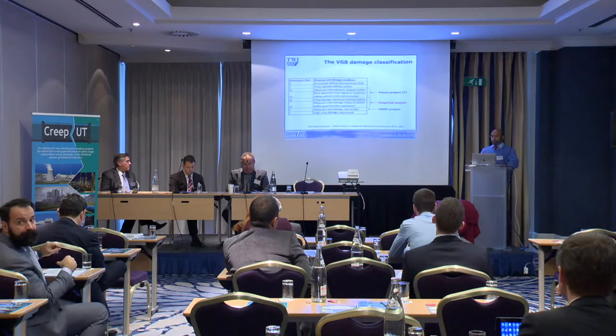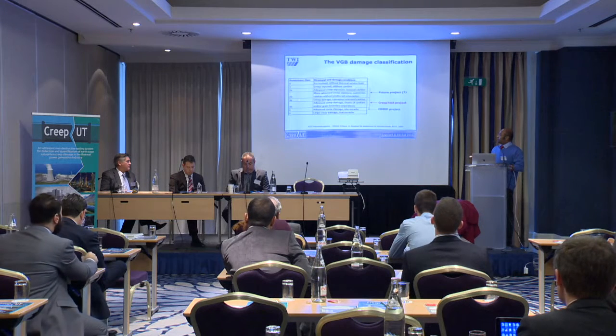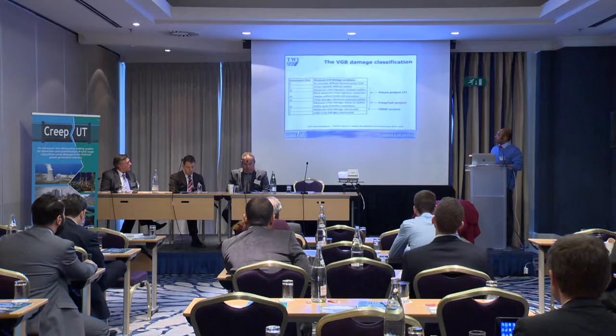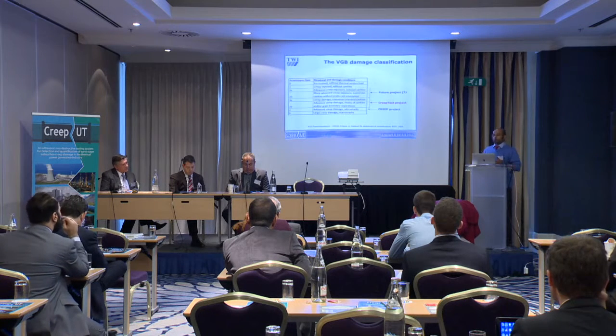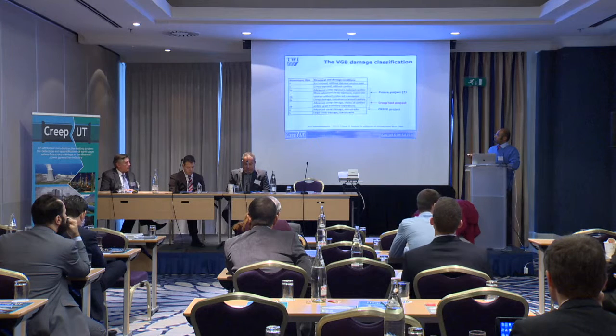So the CREEP project, as stated here, these tables are a bit outdated now, but this is a slide from that project earlier on. And we set out to solve an inspection problem and found examples of damage at level 4. So the client gave us a specimen in which we weren't successful in finding level 3A, 3B, so it was not possible to prove whether it was possible to detect it or not at that level, but we certainly did find things at the level 4. And so the CREEP project, which was a UK Technology Strategy Board funded project with RWE and SSE, demonstrated that this was possible. But the CREEP test project had to work on 3A and 3B, which required some changes in the way we approach the problem.